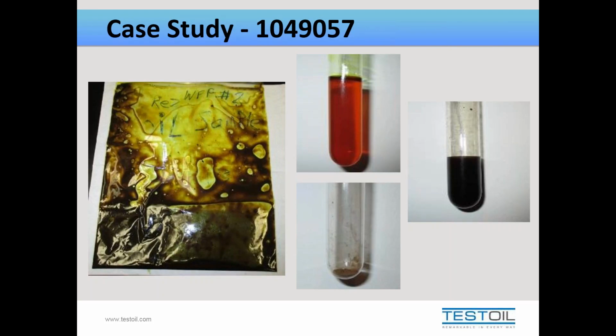And the first thing we always do with samples is we try to isolate them into different test tubes. One, we try to isolate any organic material and any inorganic material, and then the lubricant itself. And the reason for that is we like to identify the lubricant itself just to ensure that the correct lubricant was actually in the system. Because we see it all the time where we are told by a customer that lubricant A is in the system, and we're like, well, from what we're seeing, it really looks like lubricant C is in there. So we just like to confirm that information, because if they believe that there is one type of lubricant in there, but really it's a different one, that could be the root cause of the issues itself.